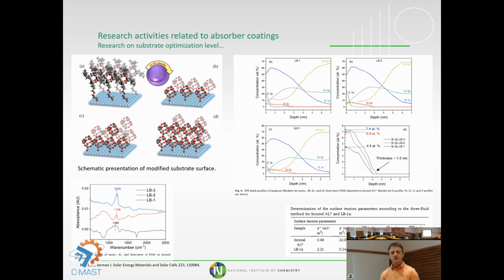They were really very, very successful with the aerosol deposition. They produced such a dense coating that after 800 or a few thousand hours at 800 degrees, there was no indication of oxidation. But the problem was that we couldn't add the black pigment because the properties of the black pigment are not the same, and that was the main problem.